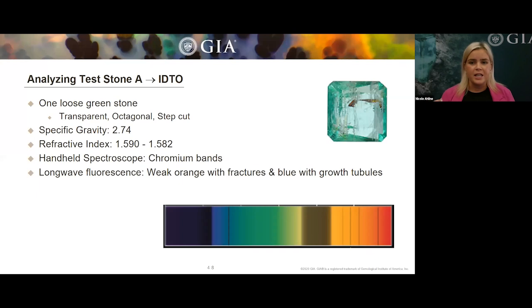Its specific gravity is 2.74. It has a refractive index of 1.59 to 1.582. The gemologist is probably now leaning toward beryl. It's green in color. Does it qualify for emerald? So they're going to check with the handheld spectroscope for chromium bands. If they're present, that's great. And because it's an emerald, they're going to hit it with long wave fluorescence, and it's got weak orange with fractures, and blue with those growth tubules.